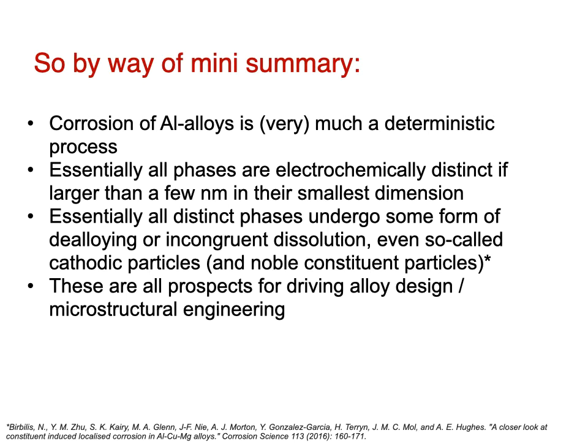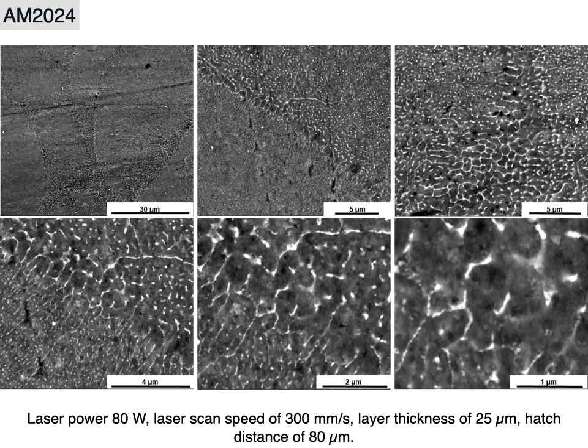So I'm going to show a couple of examples that drive home this sort of corrosion metallurgy, so to speak. But it really is a renaissance now, because if you think about the way that these alloys are dissolving and what the surface looks like as it kinetically develops, that's also very, very relevant to protection strategies and targeting corrosion protection strategies. So let us now look at additively manufactured 2024, which is an aluminium copper magnesium alloy prepared here by selective laser melting.